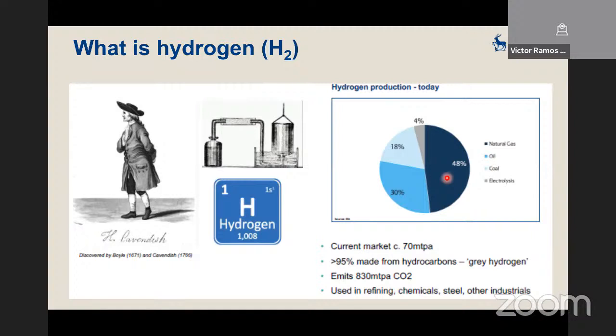About half of the hydrogen produced is from the cracking of natural gas using a thermochemical process. So it's still a very low quantity, about 70 to 80 million tons per year is produced. When you use fossil fuels, or coal for that matter, to produce hydrogen, it's called gray hydrogen because you generate carbon dioxide. But if you sequester or capture the carbon dioxide, that's labeled as blue hydrogen.